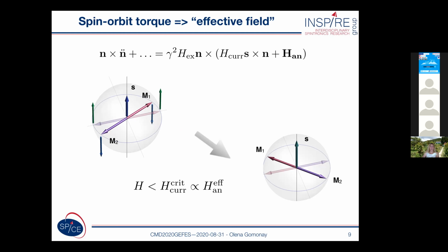And what we found out is that if the spin polarization is applied perpendicular to the lattice magnetization, then the current can effectively work as a field, as a potential force. And this is seen in the left panel. So the current in this geometry creates torques labeled as T current, which could be exactly compensated by the torques acting from the anisotropy field of the sample. And in this case, the current does not induce rotation or fast dynamics of the Néel vector. In contrast, it induces tilting of the Néel vector from its initial state, as shown in the right panel.